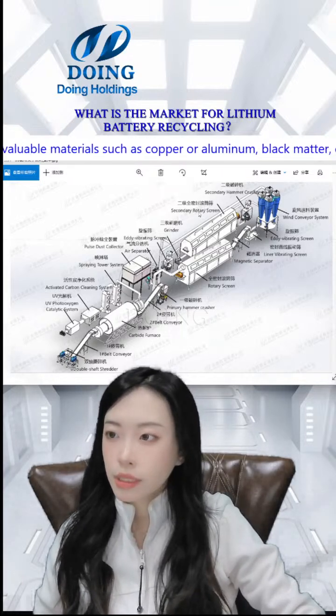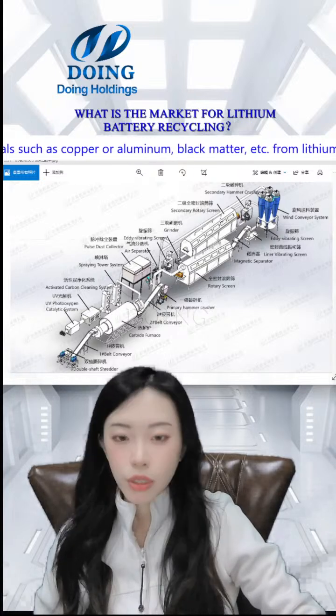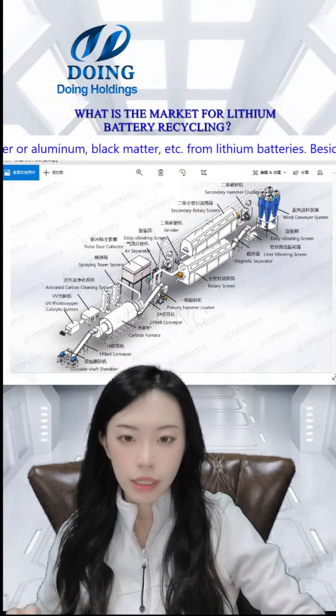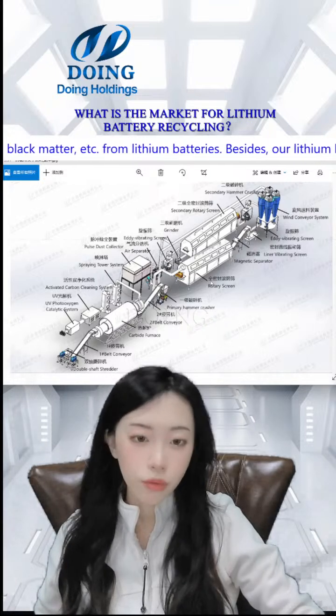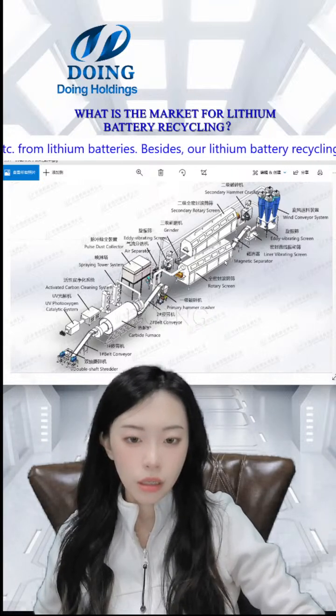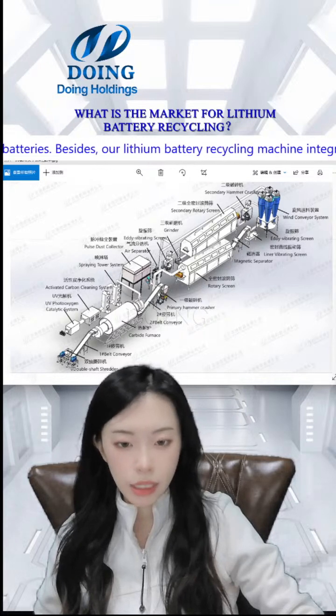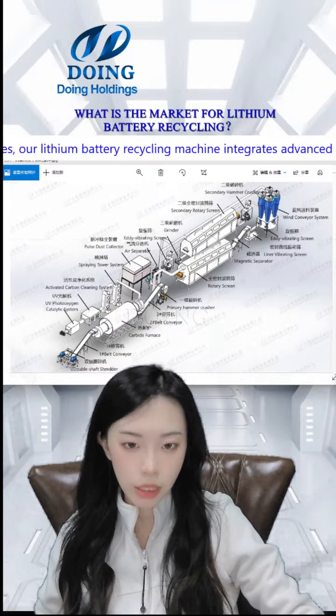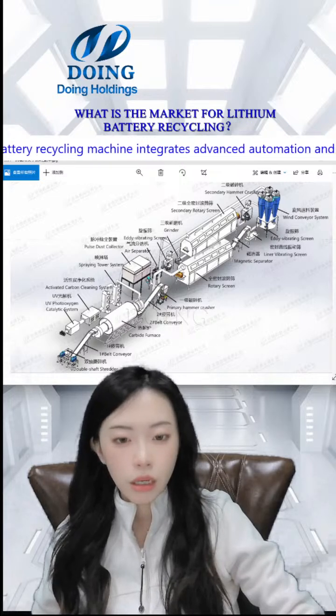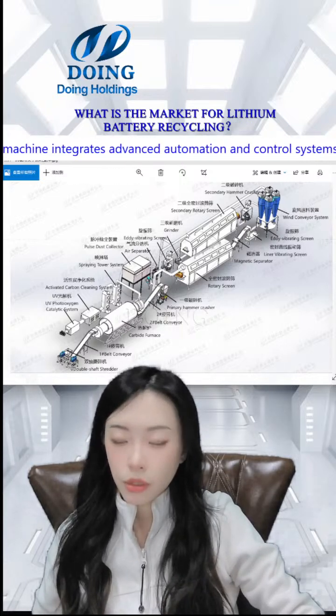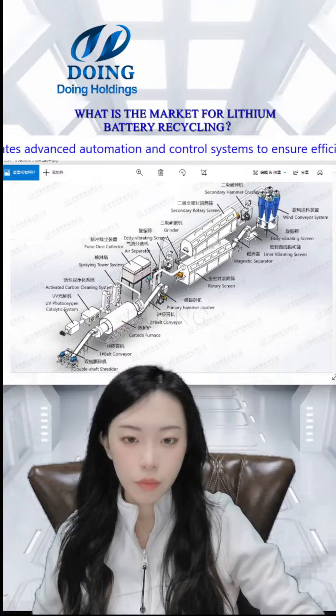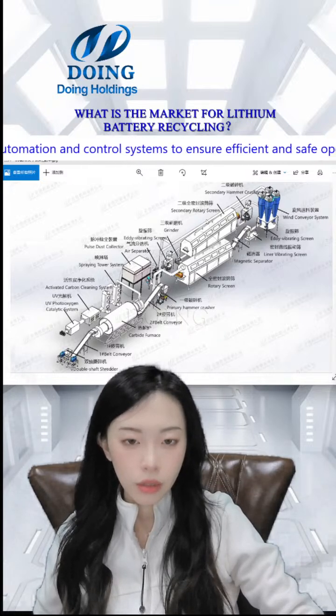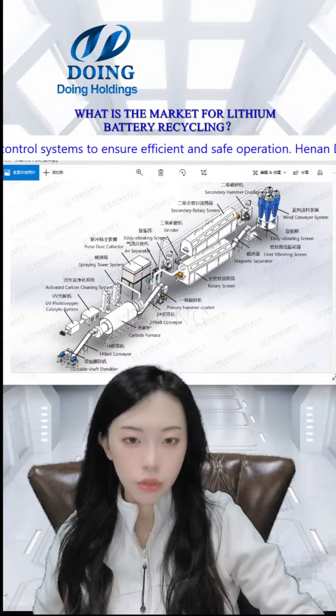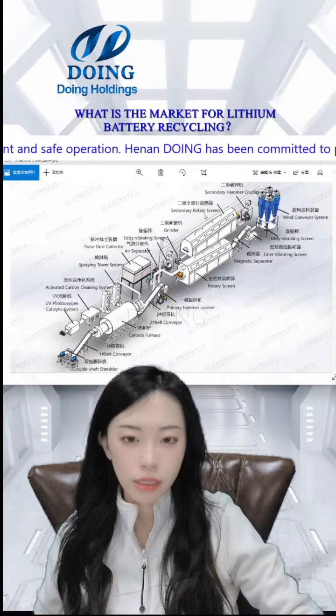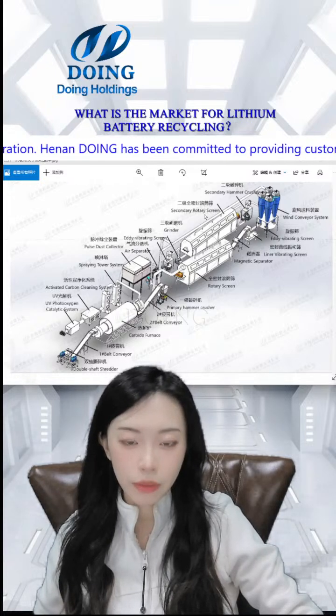Then also the secondary rotary screen. This rotary screen is a little bit smaller than the first rotary screen. The common size is 6 millimeter, and this is 4 millimeter, and the screen inside is not the same. This is a smaller screen, 140 mesh, to control the black powder. In this step, we will collect 95% of the black powder.